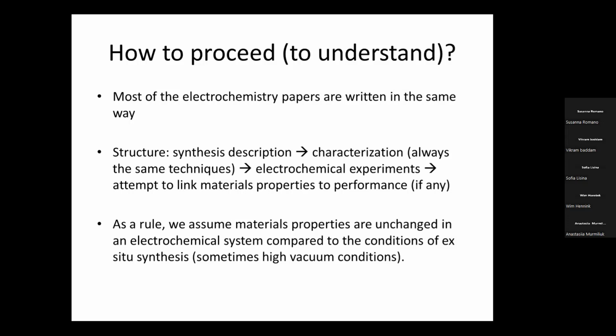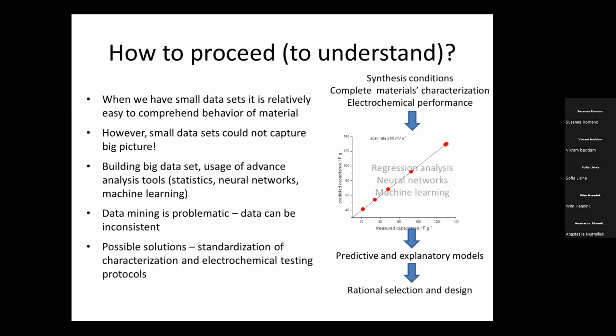But there is also another problem: as a rule, we assume that material properties are unchanged in electrochemical conditions compared to the conditions under which we characterize this material. For example, if you do XPS, there are high vacuum conditions. In electrochemistry, you have solvent, you have extreme electric fields at the interface and so on. So I really doubt that the material that you see by XPS is the same as the material that shows the electrochemical performance that you actually investigate. We do have to switch to some in situ techniques, which I believe are the next step closer to the understanding. But then there is also another possibility.